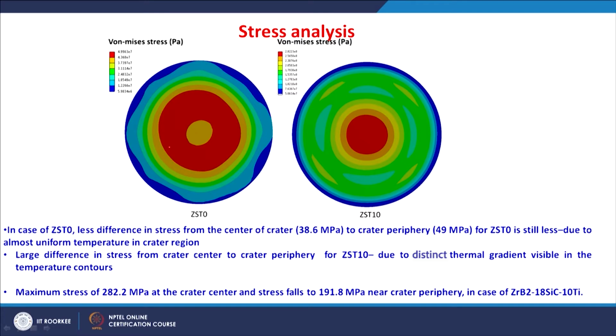So, the stresses are around 38.6 MPa in the center of the crater to 49 MPa for the crater periphery. You can see here 49, this is 10 power 7. So, it is 38 to 49 MPa if you move from the center of the crater to the crater periphery. This small difference in the stresses from the crater center to the crater periphery for ZS T0 is because of the small difference in the temperature in the crater region. So, almost uniform temperature is maintained. So, you do not have any difference in the stresses.